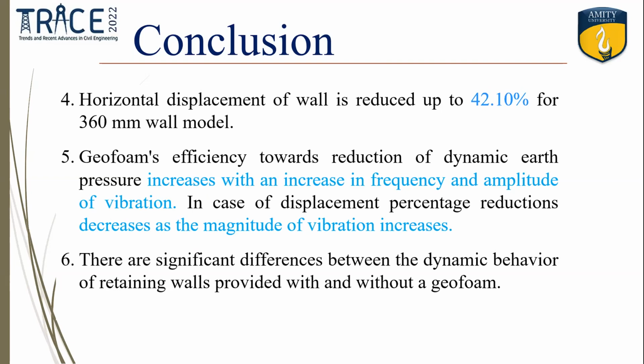Geofoam efficiency towards reduction of dynamic earth pressure increases with increase in frequency and amplitude of vibration, while the exactly opposite happens in the case of horizontal displacement as the magnitude of vibration increases. And by using the geofoam material as a deformable inclusion, we can see the significant difference between the dynamic behavior of the retaining wall.